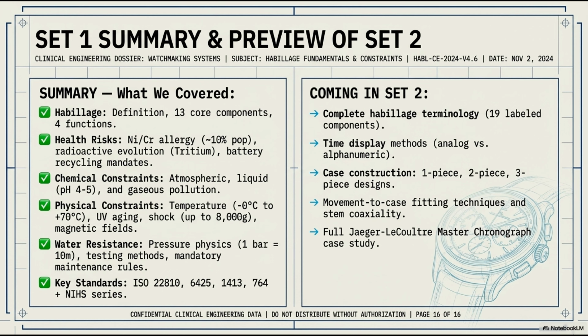We analyzed the grueling chemical constraints of atmospheric and liquid pollutants, and saw graphic evidence of sweat corroding solid steel. We mapped the physical constraints, surviving a 70 degrees Celsius temperature swing, UV degradation, 8000G kinetic shocks, and magnetic fields. Finally, we decoded the physics of water resistance, hydrostatic pressure, and the strict ISO standards that verify a case's integrity.